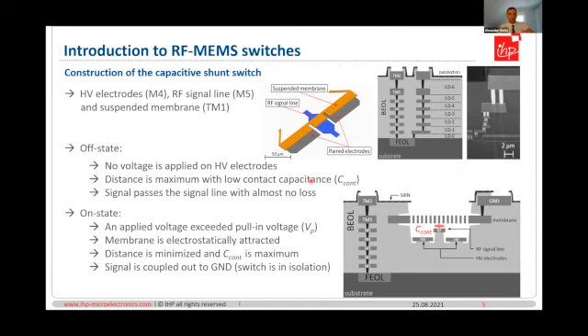As a switch, there are 2 states, the on and the off state. In off state, no voltage is applied on the HV electrodes. The distance is maximum between the signal line and the membrane, and the capacitance is low. The signal passes the signal line with almost no loss. In on state, an applied voltage exceeds the pull-in voltage, the membrane is electrostatically attracted and the distance is minimized. So the capacitance is maximum. The signal is coupled out to ground, and the switch is in isolation.